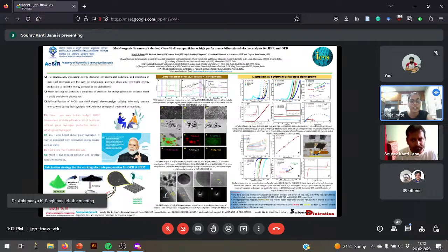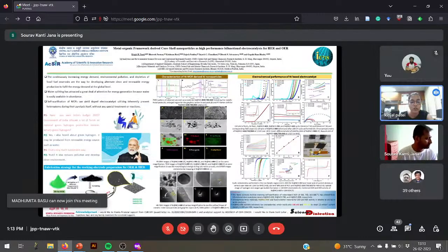the carbon matrix. So the HR-TEM image of the 800 catalyst shows spherical nickel nanoparticles, and as the resolution is increased, a wave-like morphology is also observed. Here the nickel center acts as a metal core, while the graphitic layer is observed as the shell. So a core-shell morphology has been observed. Here it can provide corrosion protection during the electrochemical performance evaluation. The SAED image shows the metallic nickel facet, which also correlates with the powder XRD data.